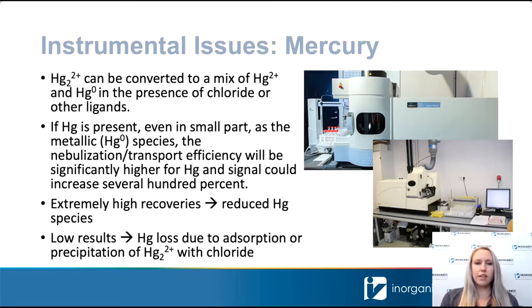On the other hand, if you're getting low results from mercury, this could be due to adsorption of your mercury at some point along the way of your solution preps. So the mercury could have adsorbed to the plastic in your containers, in the materials used to prepare the solutions. So that's one issue that could have occurred.